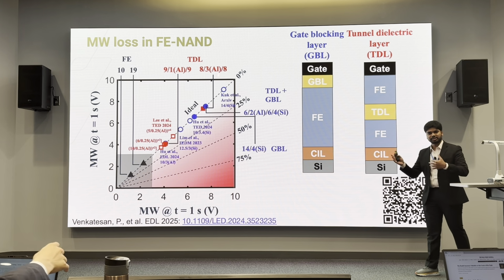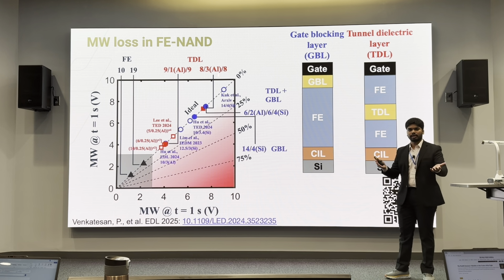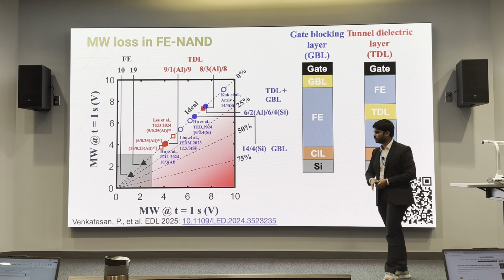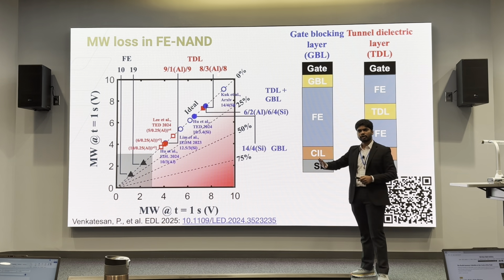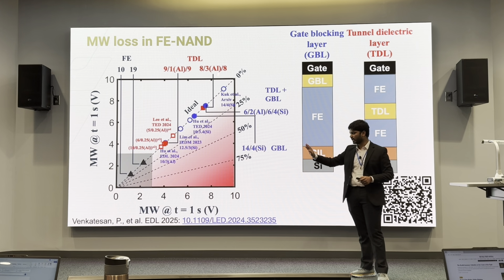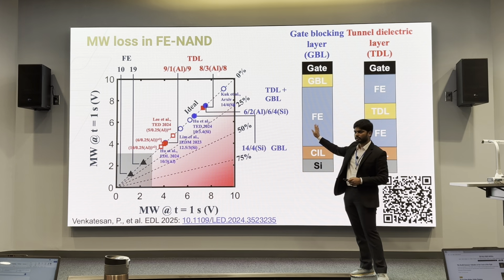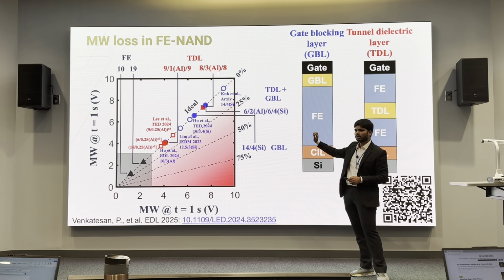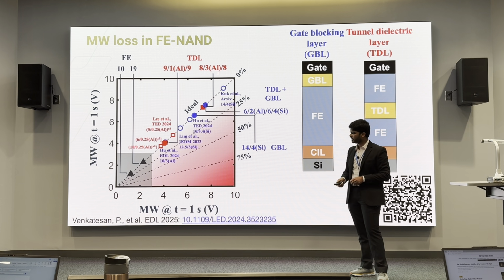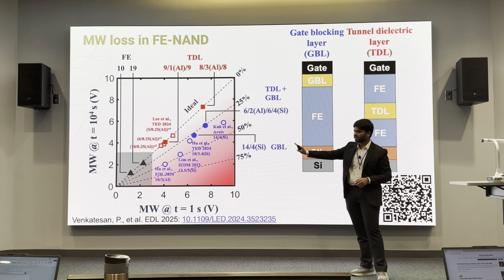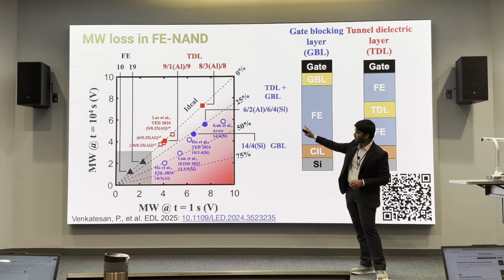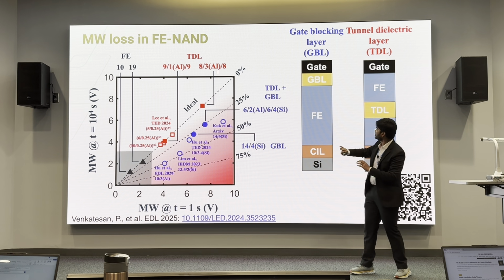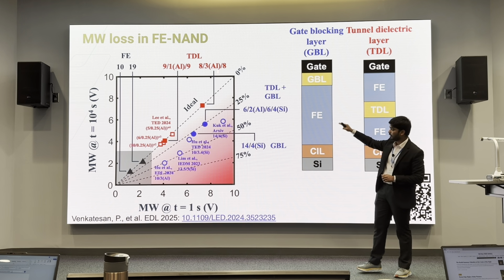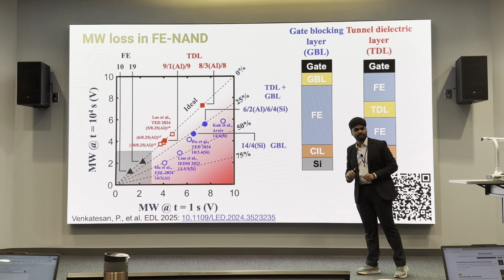Okay, now I just picked 2 materials, 2 stacks, and showed you a plot. Why should you believe me? So here we have a benchmark. I'm plotting the initial memory window on the Y and X axis. Everything is sitting beautifully along the 1:1 line, but this is not how it stays. I want you to focus on the blue dots here. After 10,000 seconds at room temperature, we see all the gate blocking layer devices, where the dielectric was inserted close to the gate at the top, have all dropped by 25 to 50%.